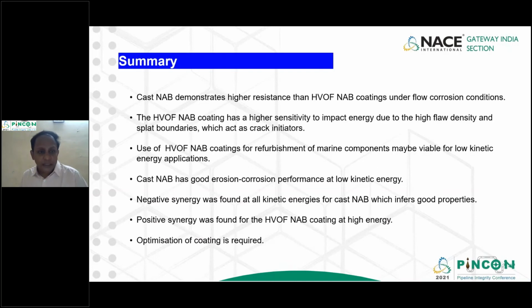The cast NAB showed higher resistance than the NAB coatings under flow corrosion conditions. The coating had a very high sensitivity to impact energy, because of its network of cracks, unmelted particles, flaw density and splat boundaries. However, the whole idea was that this coating can be used in low kinetic energy conditions, such as when refurbishing in a marine condition. The cast NAB also showed good erosion corrosion performance at lower kinetic energy, and negative synergy was found at all kinetic energies for cast NAB, which shows good properties.